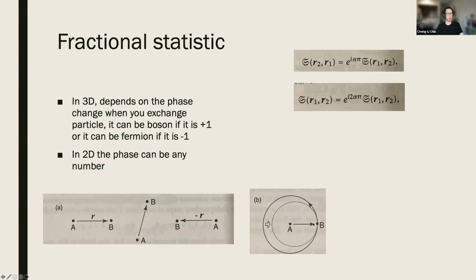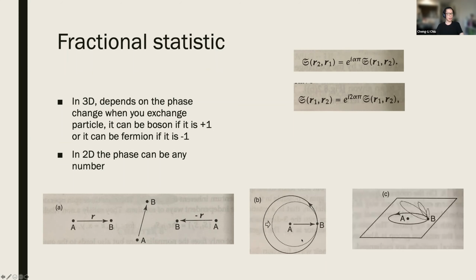So you can think of the exchange behavior as B circulating the A particle. When exchanging, you move 180 degrees, and if you want to change it back, you rotate 360 degrees. So the phase pickup when you go 180 degrees is exponential i alpha pi, and if you go 360, it becomes exponential i 2 alpha pi. And in 3D, because you have three dimensions, you can move this loop out of plane, like the dashed line, and eventually shrink the loop until it basically disappears. That means if you rotate B around again, you can continuously change it to the situation where you actually didn't move your B particle at all.